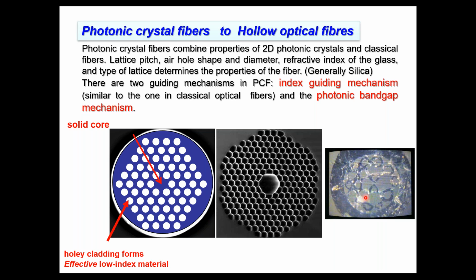The technique that we used here was that we initially fabricated hollow fibers, fibers with a hole. A large number of them were stacked inside a bigger tube, and then that was drawn. But even though it was a failure, we started working on these hollow kinds of fibers, and we found that these hollow optical fibers, when doped with some fluorescent gain medium, can very well act as micro lasers, or the WGM micro cavities that we have been mentioning for some time.